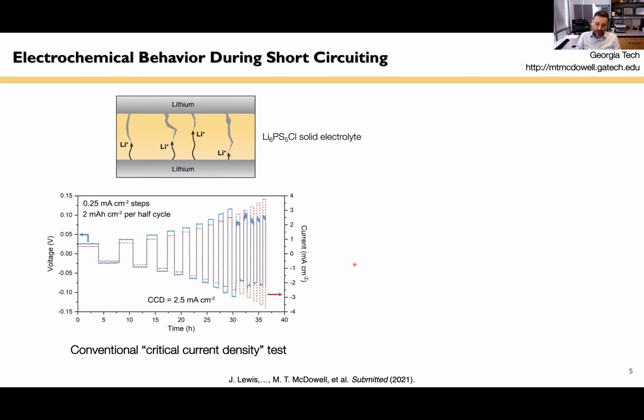Before I get into some of our results on understanding transformation mechanisms and degradation behavior, I want to provide some very new data from my group that illustrates the electrochemical degradation process seen in solid state batteries. This is the sort of information you get from normal electrochemical testing. In this configuration, we have lithium metal electrodes on two sides of a solid electrolyte material. This is the argyrodite LPS material with the chemical formula shown here. It has a high ionic conductivity. What we're probing in this experiment below is the short circuiting behavior when we have lithium metal that, instead of growing in a planar fashion, grows through our solid electrolyte. This test below is widely performed in the literature. It's called a critical current density test.